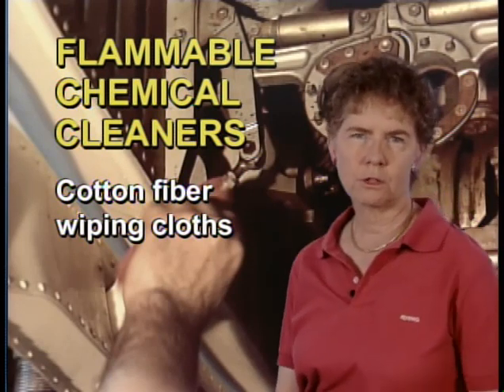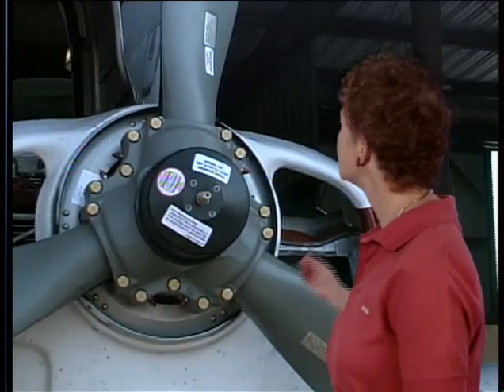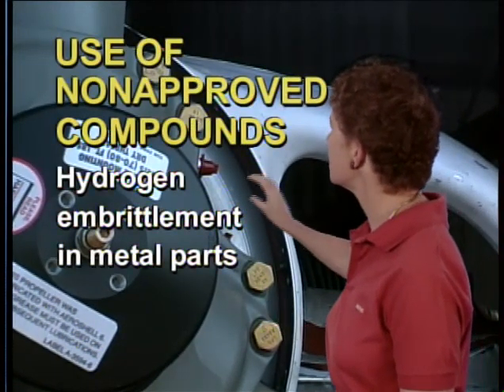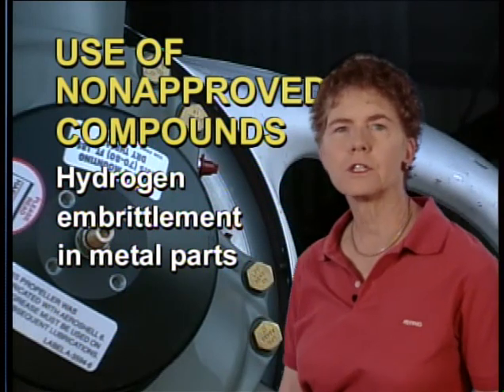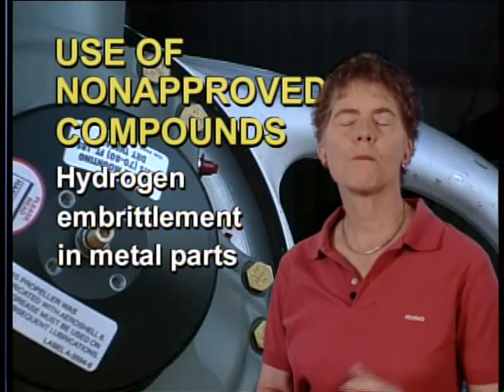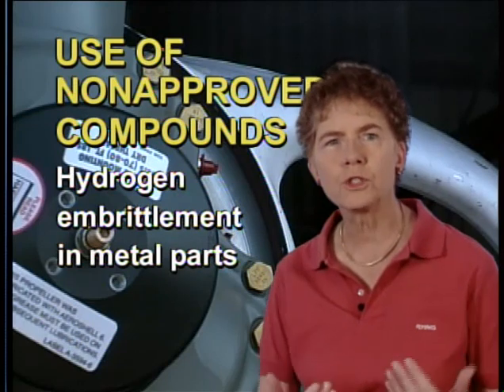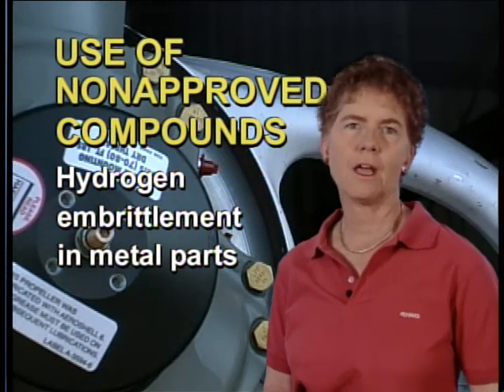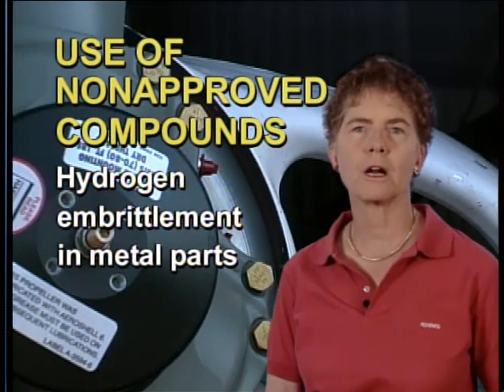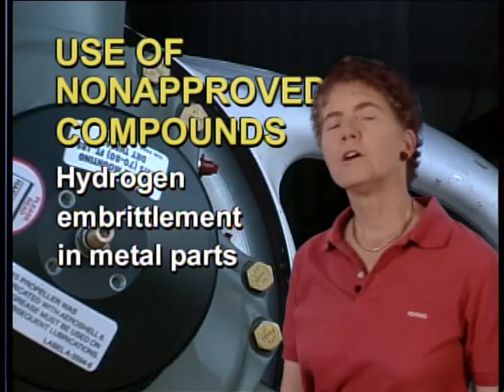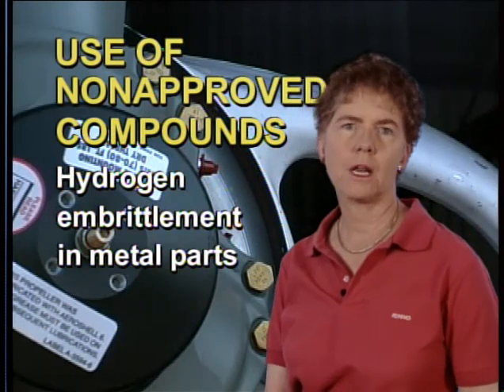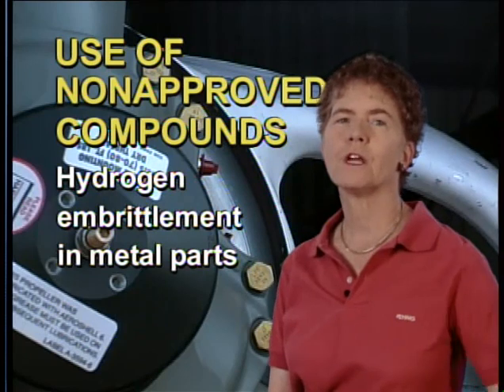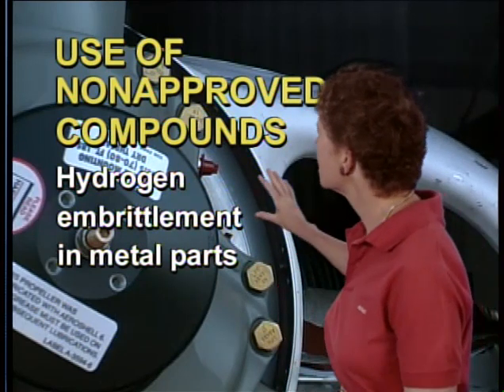Now, another concern with chemical cleaners is to make sure that you're not using ordinary or otherwise non-approved cleaning compounds when you're washing down an aircraft, like when you're cleaning the engine compartment to work on it. If you apply some non-approved cleaners on the metal parts, it can result in hydrogen embrittlement in those metal parts. The chemicals in some non-approved cleaners can react with the metal to form hydrogen gas. And this hydrogen gas is then absorbed into the metal, creating a loss of flexibility. And that can result in cracks or stress corrosion of the metal, something you do not want on an aircraft. So when you're washing an aircraft, avoid the possibility of hydrogen embrittlement in metal parts by making sure that you do not use ordinary or non-approved cleaning compounds.